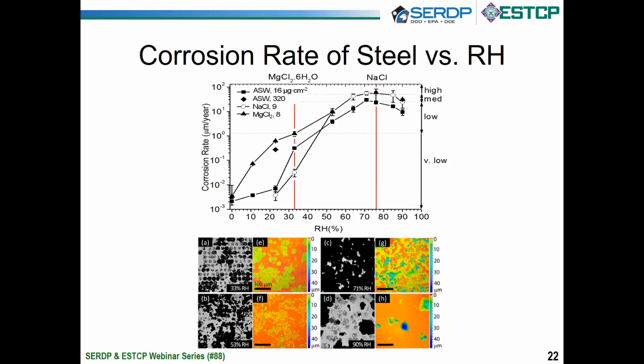For those of you familiar with atmospheric corrosion testing and the ISO 9223 standard, one of the things that they clearly note in there is that they believe corrosion happens at above 0 degrees and above 80%. So as you look at these corrosion rates from these steel panels, you can clearly see that there's corrosion occurring at moderate and or low levels, certainly down at 65, which is well below the deliquescence point. So deliquescence is the relative humidity at which a salt crystal will turn into a puddle of corrosive fluid, in the case of sodium chloride. So you can see that as you drop below that point, we're still getting significant corrosion.